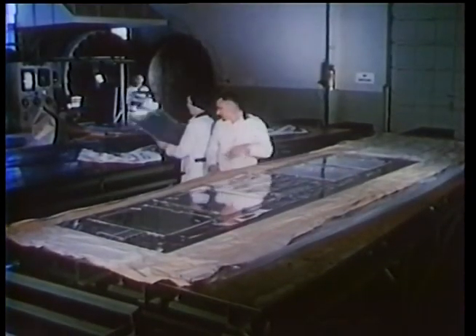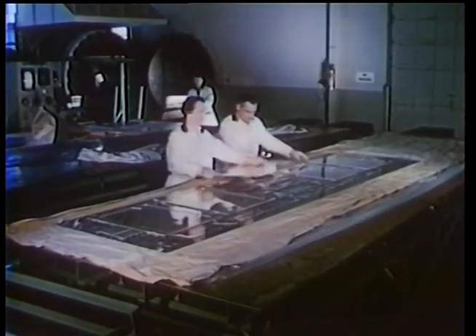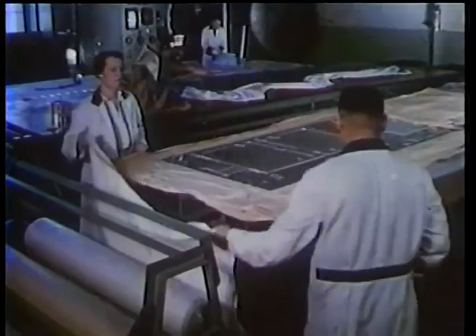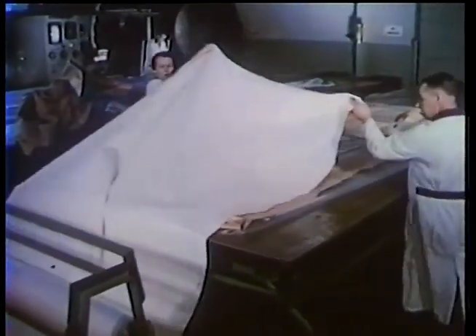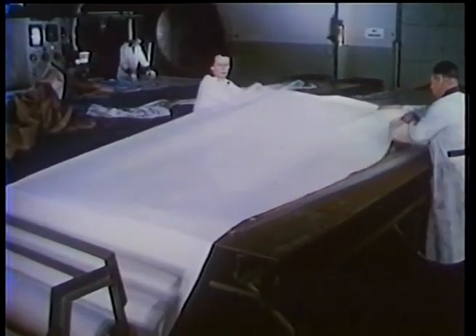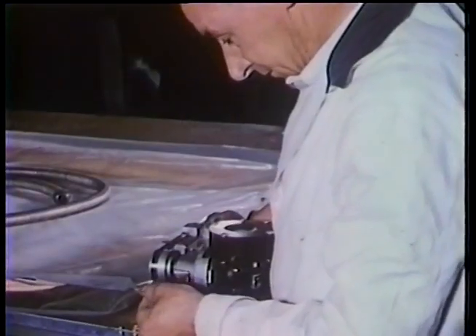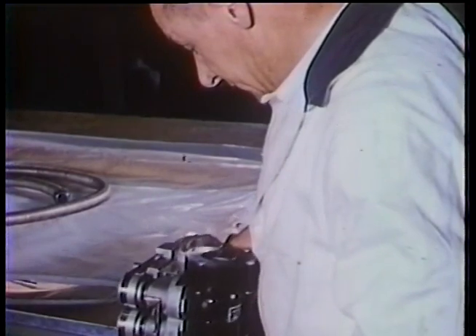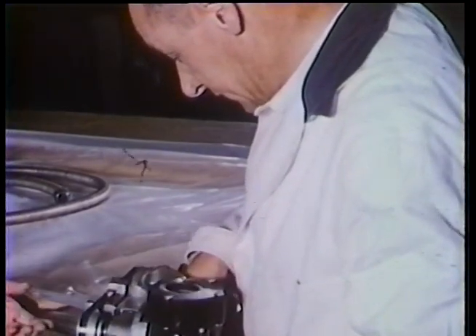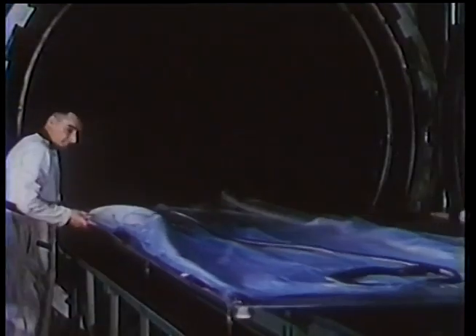Extremely high tensile strength must be achieved in the bonding together of metal components. This bonding strength is gained by use of autoclave equipment. Both components are first adhered to each other with bonding material and then wrapped in glass cloth. After this, the assembly is sealed inside a plastic bag which has a vacuum attachment. The air is exhausted from the bag, forming pressure to hold the components in bonding position.